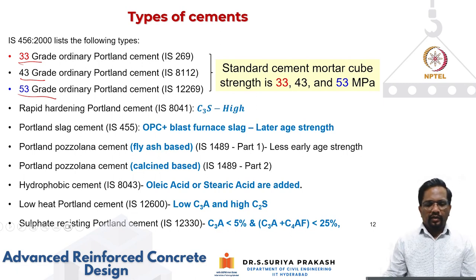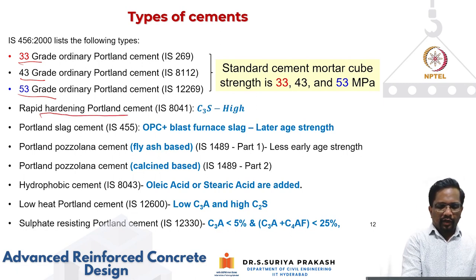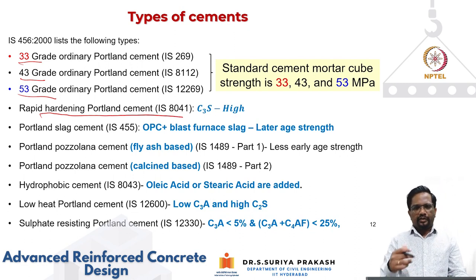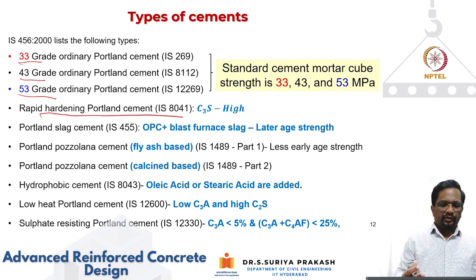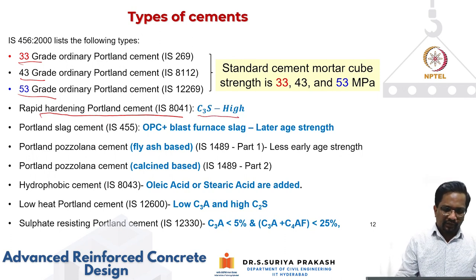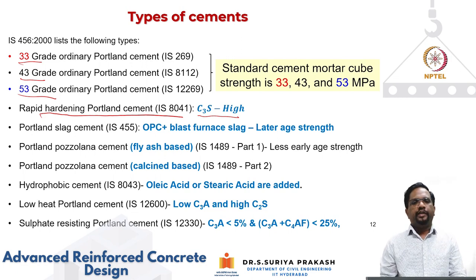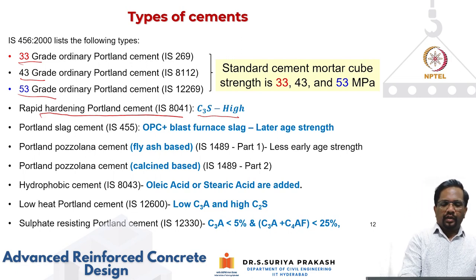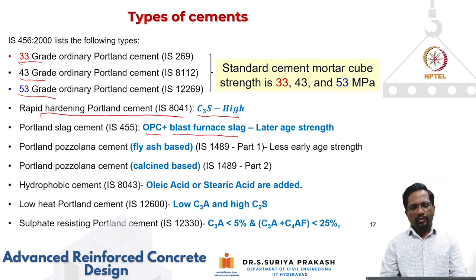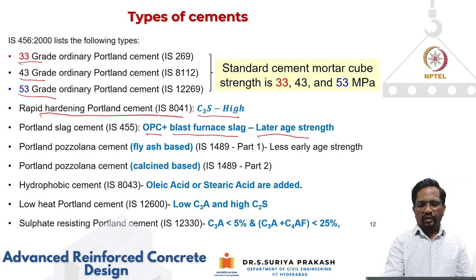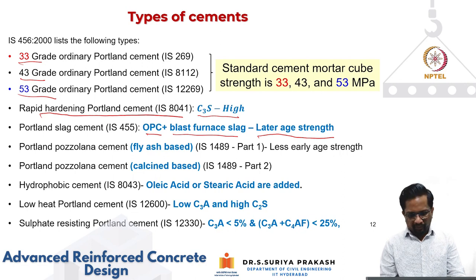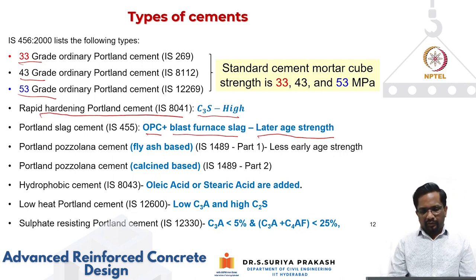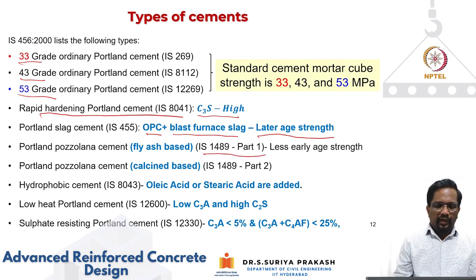We also have another type of cement that we call rapid hardening Portland cement. Previously we discussed the degree of reaction: C3S reacts faster. So if you want rapid hardening concrete, then your cement also should have higher C3S. Then we also have Portland slag cement, and slag is one of the mineral admixtures or supplementary cementitious materials that we talked about. There they add some blast furnace slag with OPC. The advantage is that you improve the durability properties, and also you get high strength at a later age. Then we also have Portland pozzolana cement, which should conform to IS 1489, and they are based